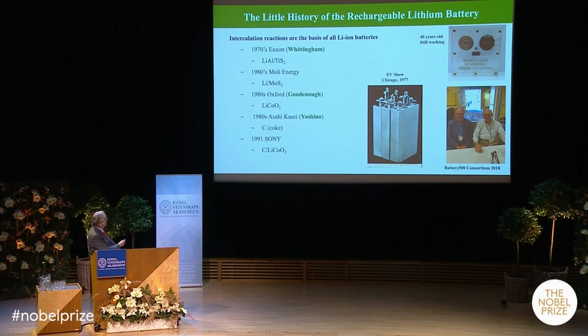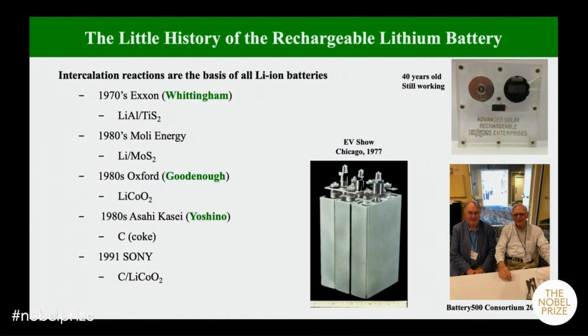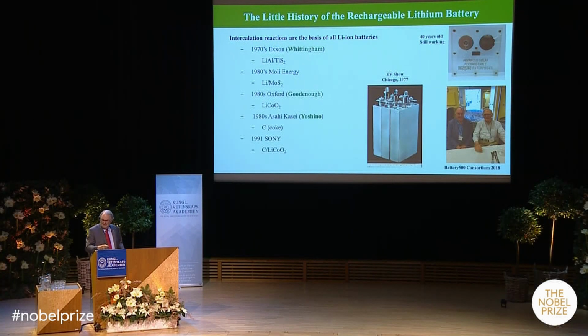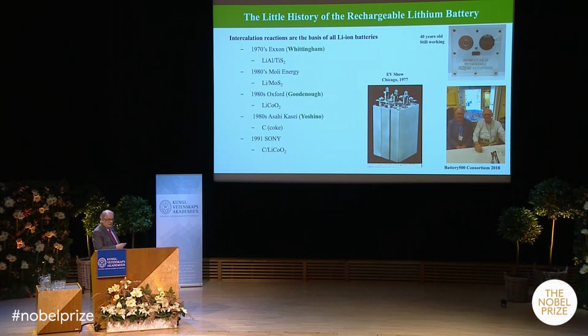So it's the 1970s when we did TiS2. Then a few years later, there's a lot of work coming out of British Columbia, Vancouver, because in Vancouver they have molybdenite as a natural ore, so they dug this out of the ground as being a more environmentally satisfactory material and built batteries of this. And this went commercial for about 5 or 6 years until they had some safety issues with it. But this used pure lithium. Then John developed the lithium cobalt oxide. Then Yoshino came up with the coke. And then it was really Sony who built, I would say, the economically successful batteries that then went into camcorders and other events and really got the electronic revolution going. And I can put this in a slightly different format on this slide.